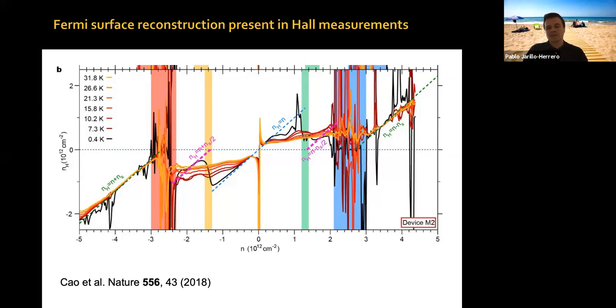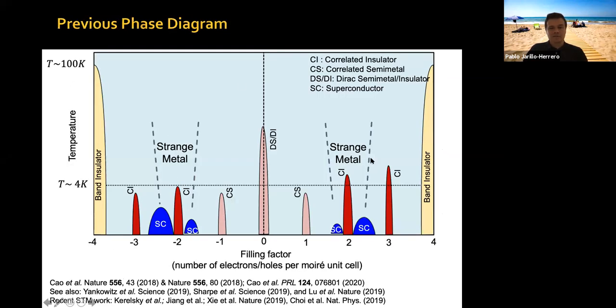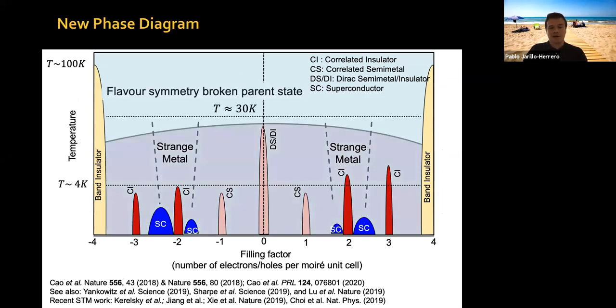So these studies show how tremendously rich the system is. And again, if this is the previous phase diagram, now, thanks to these studies, and Ali has done experiments that reached pretty much the same conclusions with a very different technique, so this is very robust, we have a new phase diagram. Already at high temperatures, at least of order 30 Kelvin, probably actually higher, we have a flavor symmetry broken parent state before and after each integer. And that is the background on which all of this low temperature physics, correlated insulator states, superconducting states, etc., develops at low temperature.